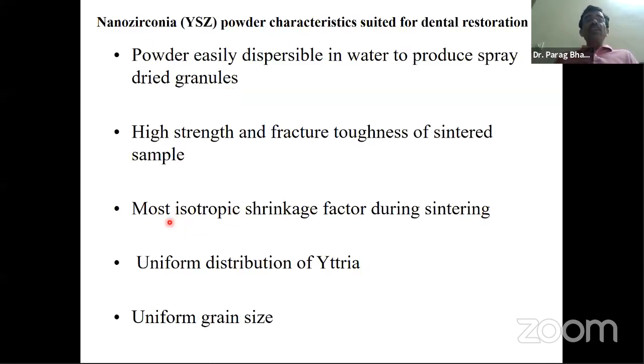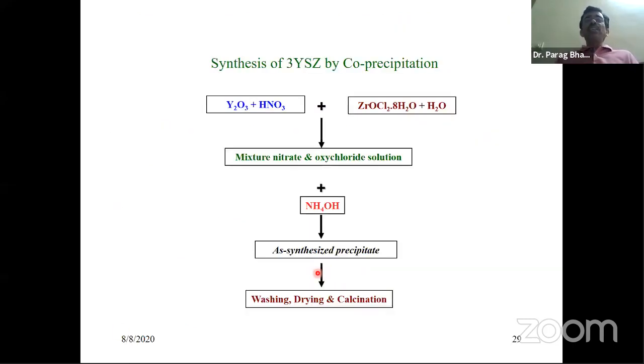One very important thing is my powder must have this kind of characteristic, that it should not be anisotropic, such that finally when the crown is made, the crown, when it is sintered, should not have anisotropy. Otherwise, it will not fit in the patient's mouth, right? Because the crown, when it is made by milling, is a little larger, and if it shrinks isotropically, then it will shrink and fit the patient perfectly. Okay, and these are some other details. I don't want to go into it. This is the process we use.